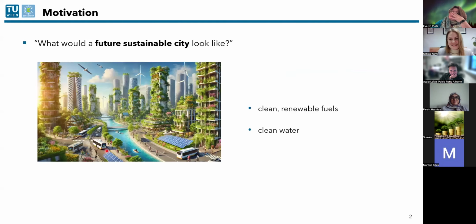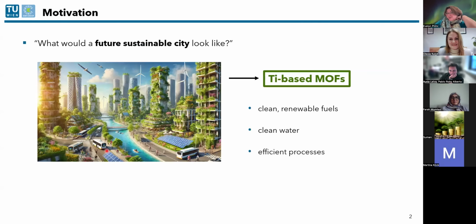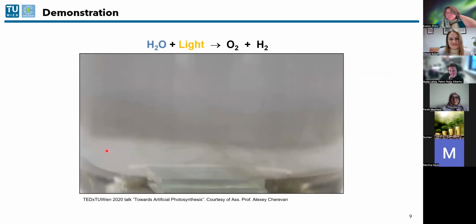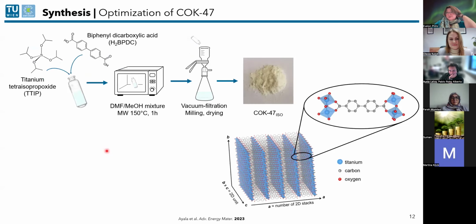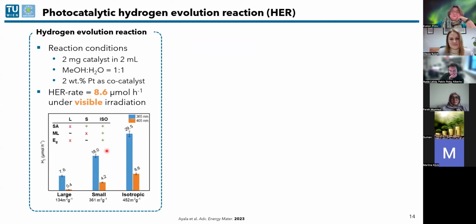Okay. So Suman basically asked on slide 14, because you were just scrolling through, why was 2 weight percent platinum selected as the co-catalyst, and what was the platinum precursor used? Yeah, very good question. So the precursor is hexachloroplatinic acid. And the weight percent, we did some optimization. So we started at, usually you need very little, 0.2 weight percent and we went all the way up to 5 weight percent. And then you get this classic volcano plot where you see that at around 1.5 to 2 weight percent, you have the optimal platinum amount.